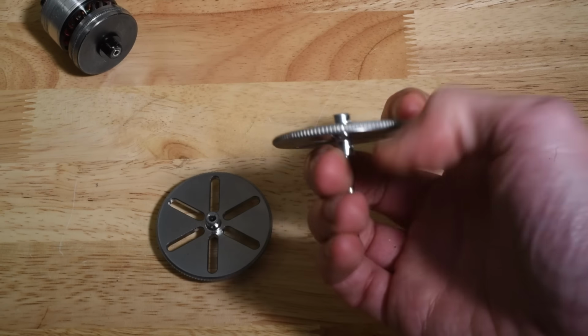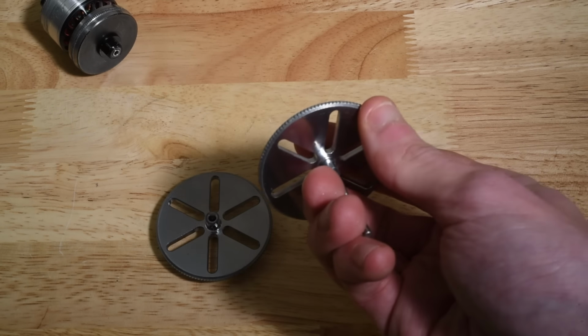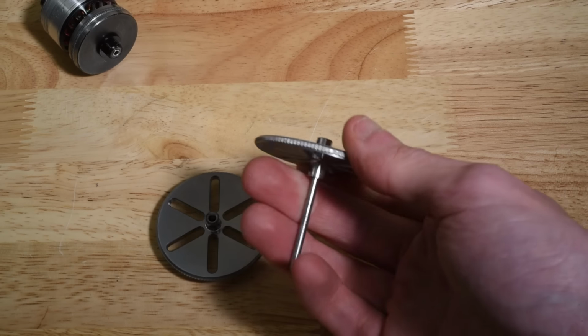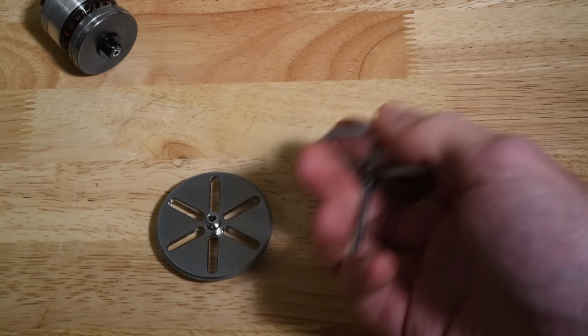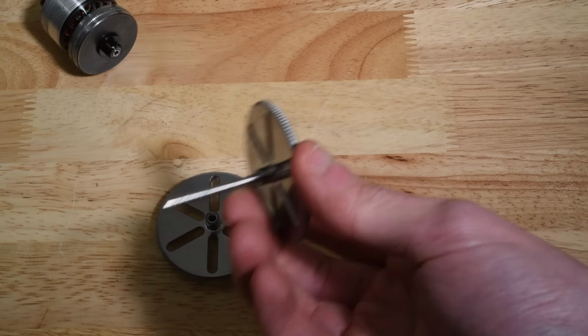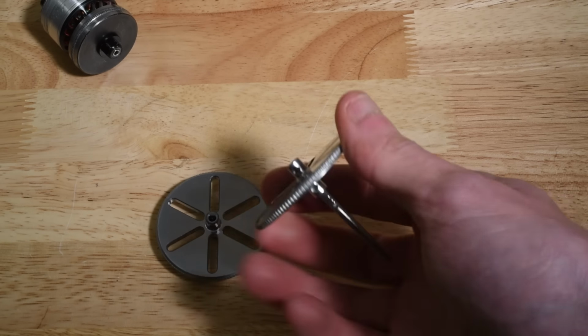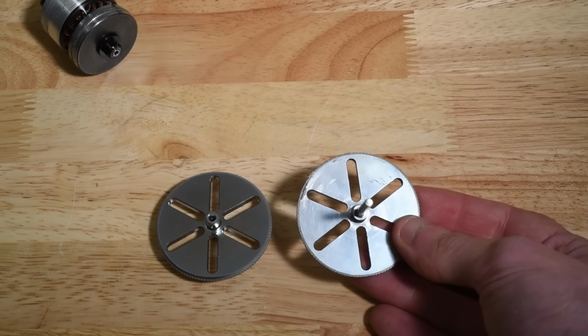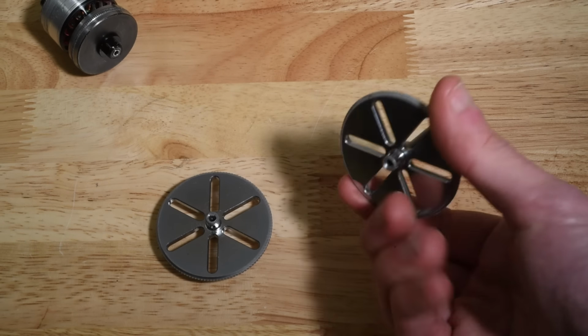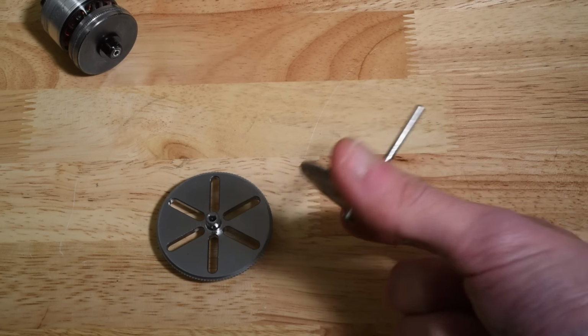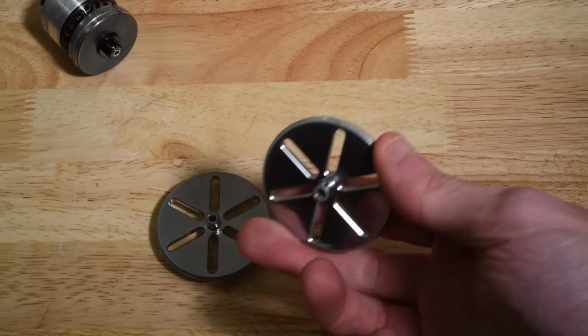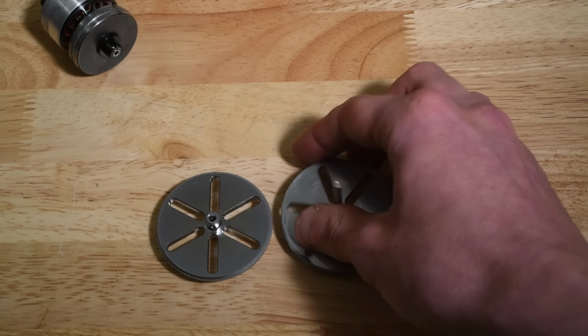And this causes the deposits to be wide and spread out. And because the wheel has sloped edges, this causes a ton of extra flash or just material to be extruded from the edges and make more or less unbonded sections around the deposit. So that was super annoying, and these wheels were not cheap from PCBWay. They were probably $30 or $50 a piece, I don't remember, but they were very expensive for what they are.